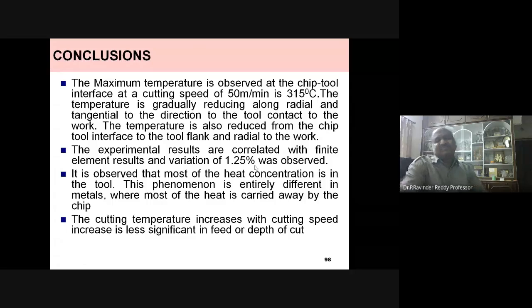So to conclude, the maximum temperature is observed at the chip tool interface at a cutting speed of 50 meters per minute. That is 315 degrees centigrade. The temperature is gradually reducing along the radial and tangential directions of the tool contact with the work. The temperature is also reduced from the chip tool interface to the tool flank and radial to the work. The experimental results are correlated with finite element results, and the variation is observed to be 1.2% at steady state condition. It is observed that most of the heat concentration is in the tool. This phenomenon is entirely different in metals, where most of the heat is carried by the chip.